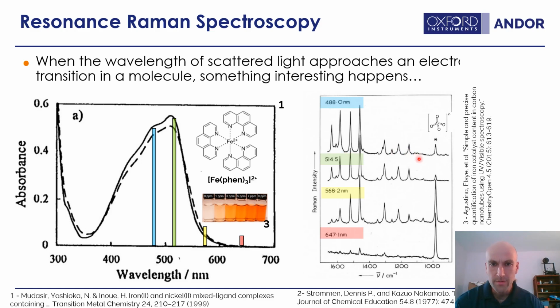Here, this spectrum actually shows an internal standard. So in the solution are sulfate ions that Raman scatter as well. They scatter non-resonantly, so we don't have to worry about them being changed as we change the frequency of our light to be scattered. So this is an internal standard. It's something that's in with the sample or in with our unknown, that provides a steady peak that we can calibrate off of. And that internal standard is really helpful, because you can see here the internal standard dominates. The spectrum of our coordination compound is very weak.